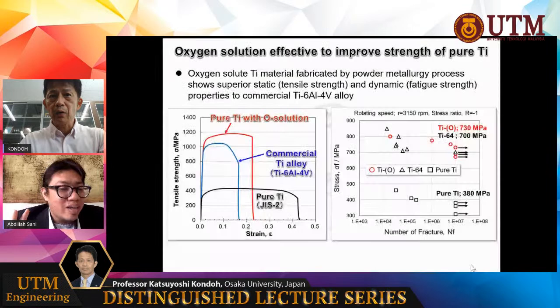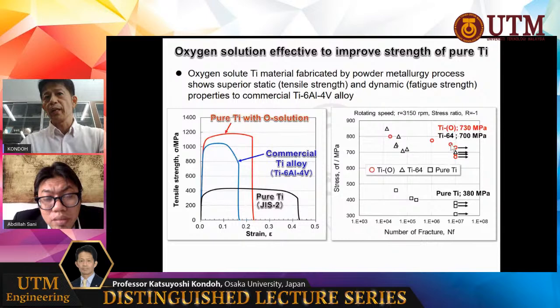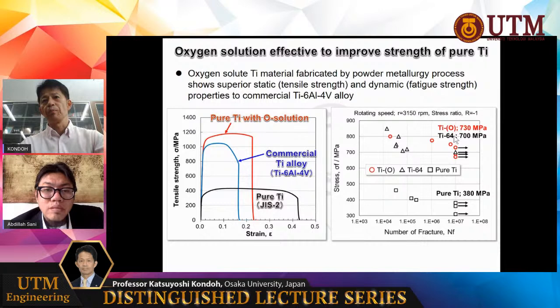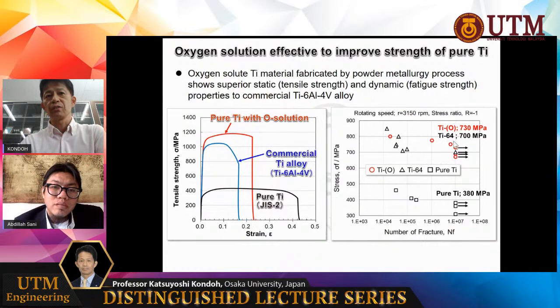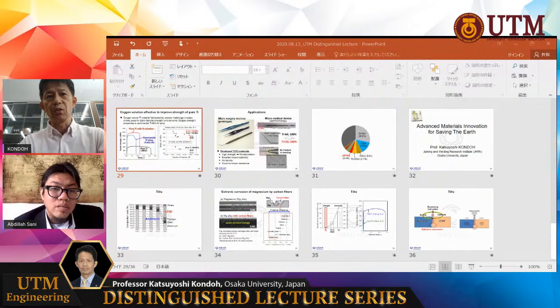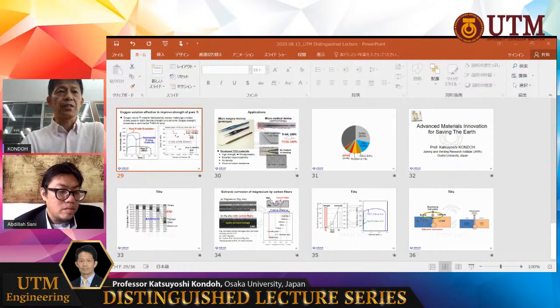We can see now. So the red one is the titanium oxygen, and the blue one is the titanium 6-4. And this one is the fatigue test results. Red mark is the titanium oxygen, and the blue black one is Type 6-4. So we understand the higher fatigue strengths of titanium with oxygen, right? Basically, we obtained the titanium iron oxygen that showed close to 800 megapascal at the fatigue limit. So that is quite large compared to Type 6-4. But unfortunately, at this moment, we have no evaluation of creep resistance.